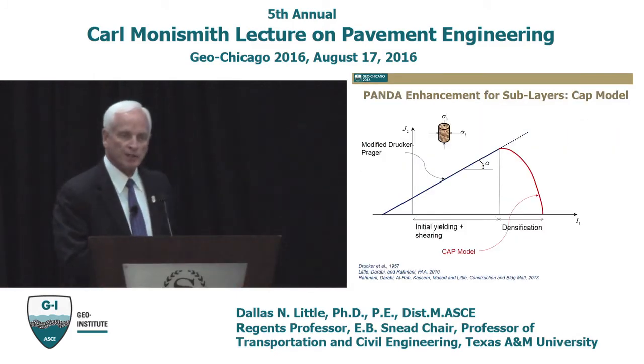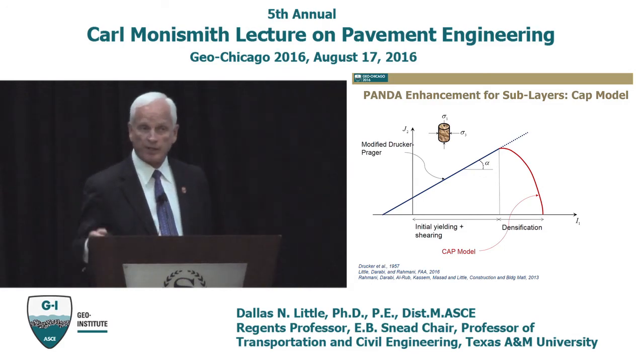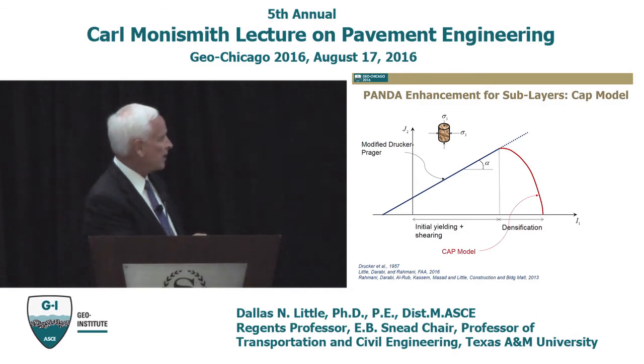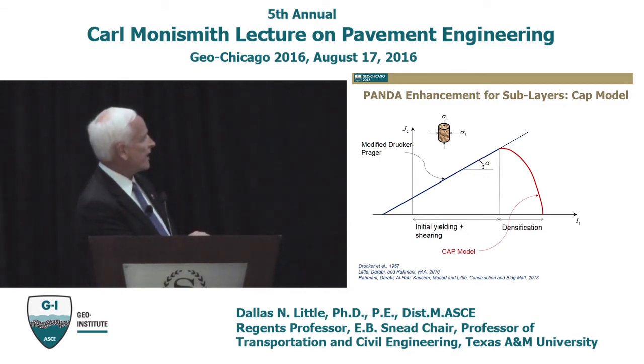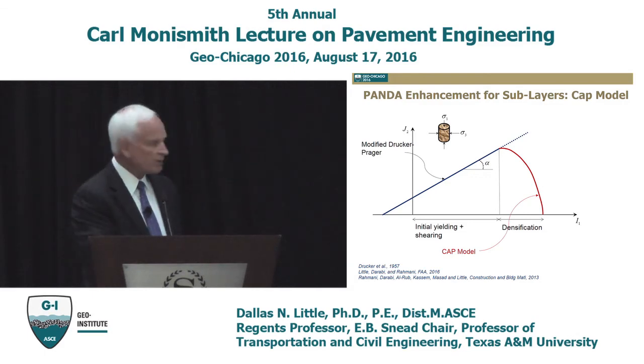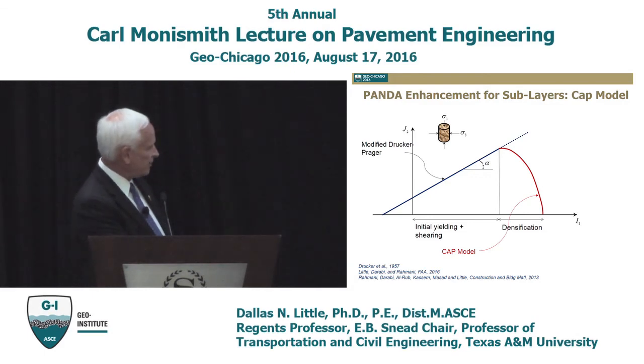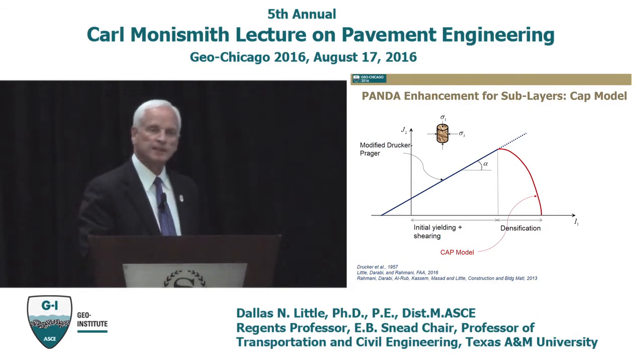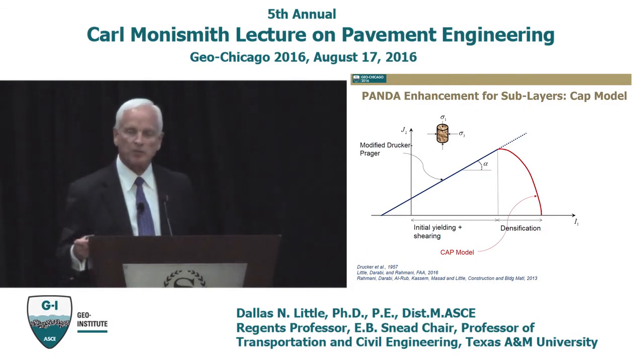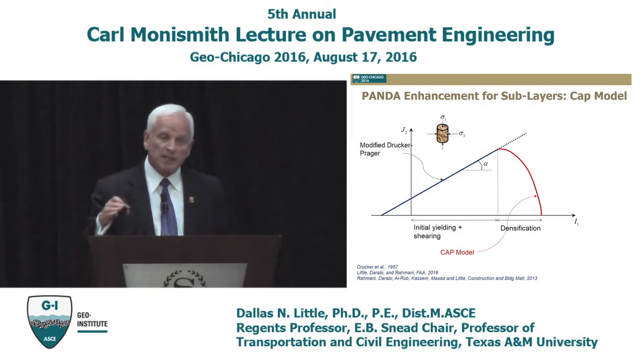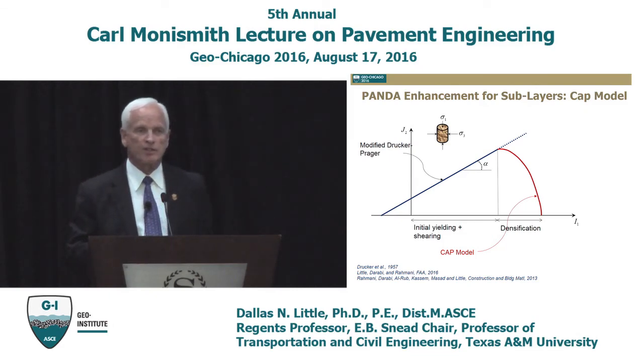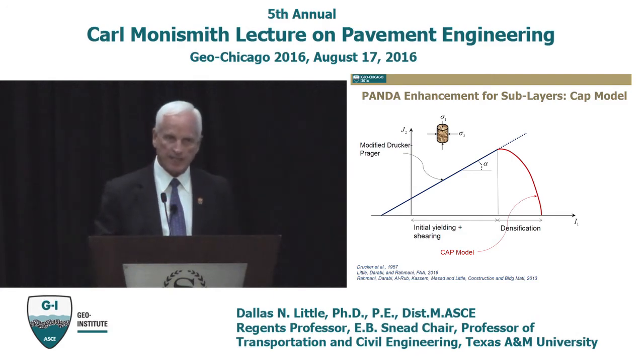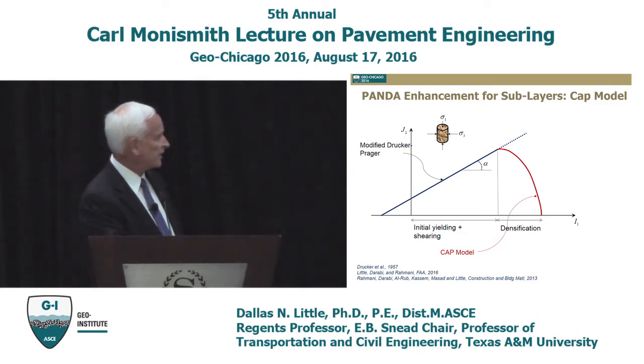We tried many different models to try to mimic what occurred at the FAA test facility. And what we came up with was a modified Drucker-Prager with a cap. And that's nothing new. As a matter of fact, Drucker introduced that back in 1957. So we're not claiming that we came up with this model. We're just applying this model, probably a little bit of a modified version, to see if we can actually understand the data that we're getting from the FAA facility.